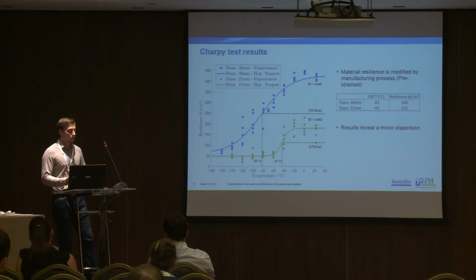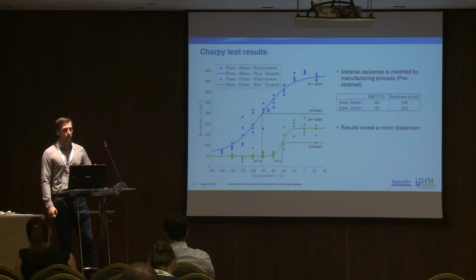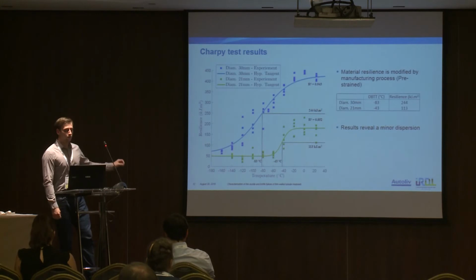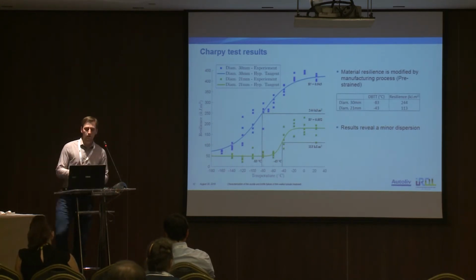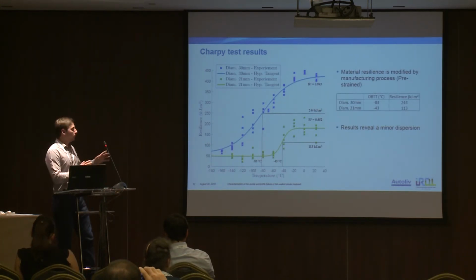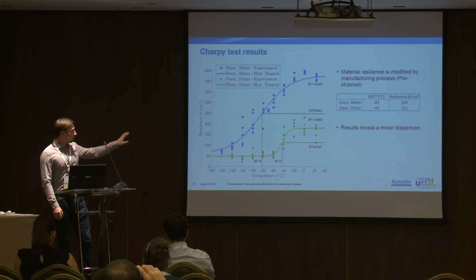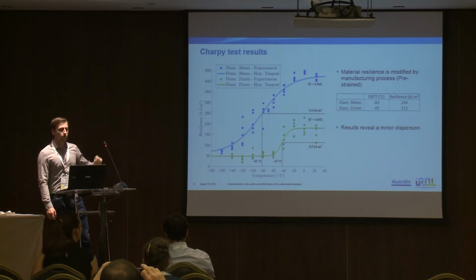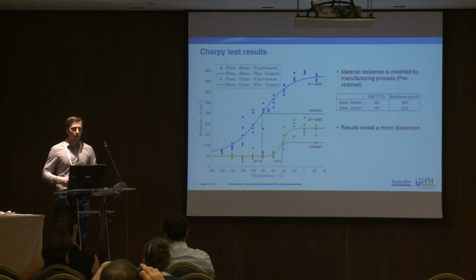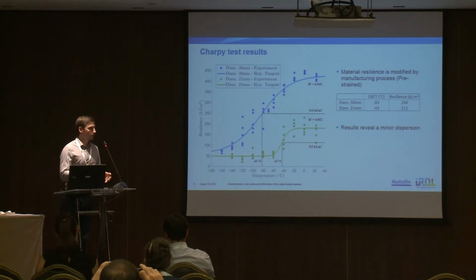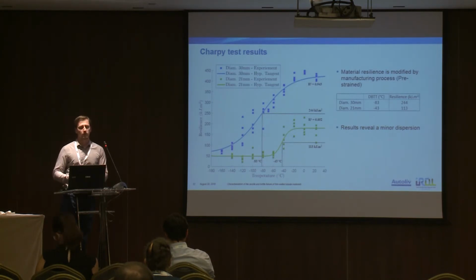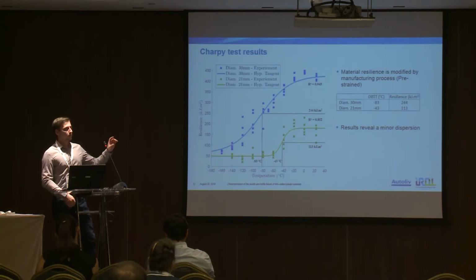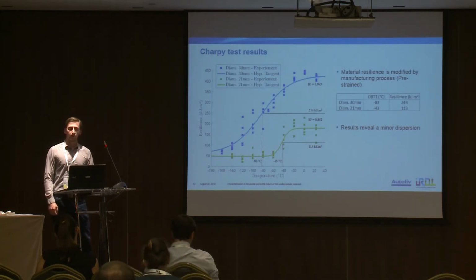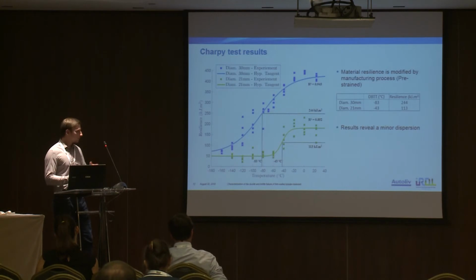So, once the Charpy test samples were defined, some tests were done with these 2 diameters. And as you can see here, there are really 2 different curves, and of course, 2 different ductile to brittle transition temperatures. This is due in part to the sample geometry, and also to the mechanical manufacturing process, because in order to obtain the 21 millimeter diameter, there is a cold deformation.